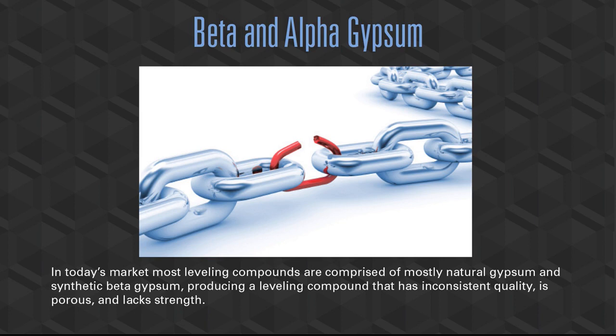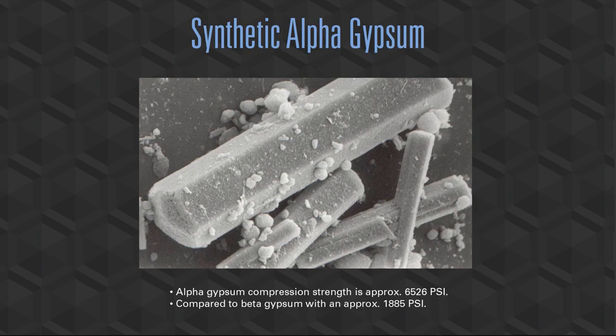So we've had really a missing link between existing gypsum, natural gypsum, and beta. We combated the synthetic with having no mold and mildew growth, but we really lacked the PSI strength that we needed to produce a quality self-leveling product and have the consistency of that product. So we have alpha gypsum used in our synthetic gypsum compounds. So alpha gypsum compared to beta, 6,526 PSI, compared to beta, which is 1885. So we can get a very high PSI strength with a controlled environment that can go over that critical substrate.